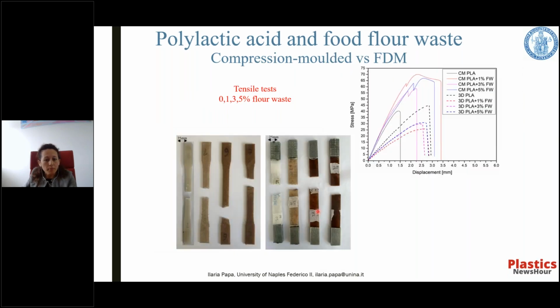In fact, we can see that the preliminary results emphasize that through compression molding, so the CM sample, it was possible to get homogeneous components and the natural filler used as reinforcement improved mechanical performances. For the additive technology, so the 3D samples, the samples obtained show a lower mechanical behavior and underline the technological issues of the technology. In fact, the main results obtained on the 3D printed specimens show that the Young's modulus and the tensile strength of the composite specimens are mainly worse than those characteristic of the neat PLA, that is this black line for both technologies in this graph.